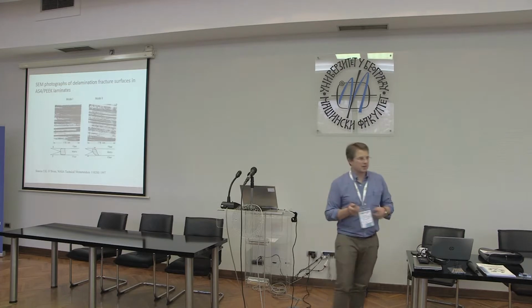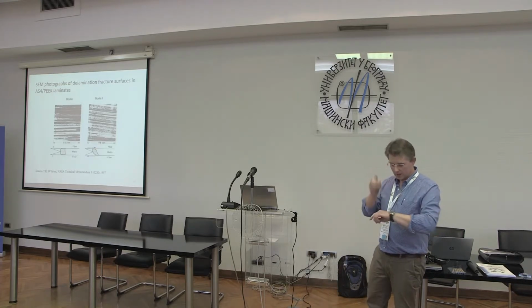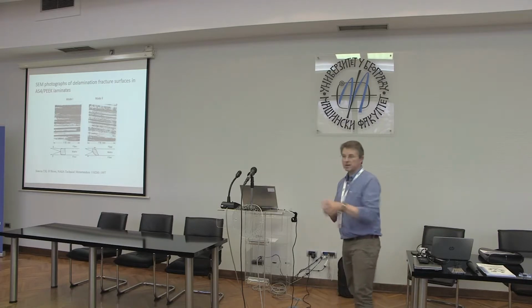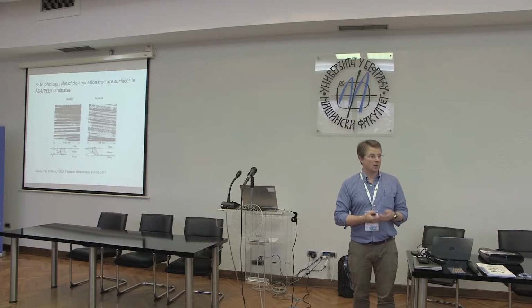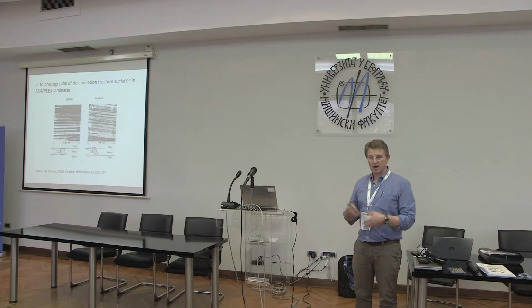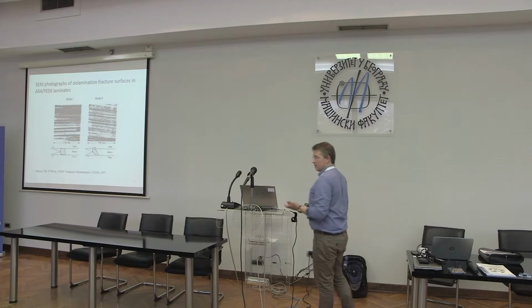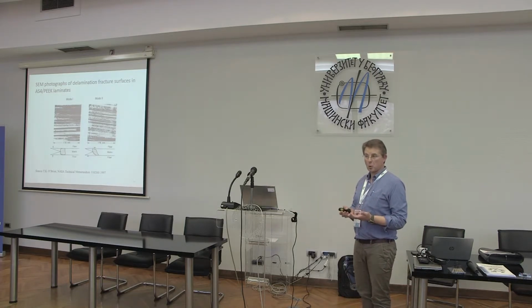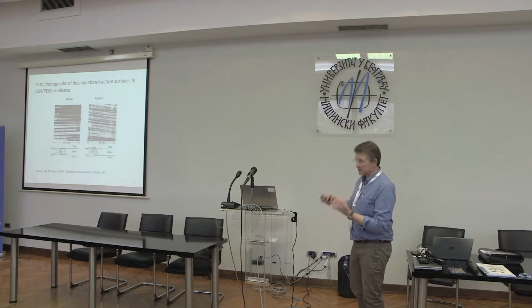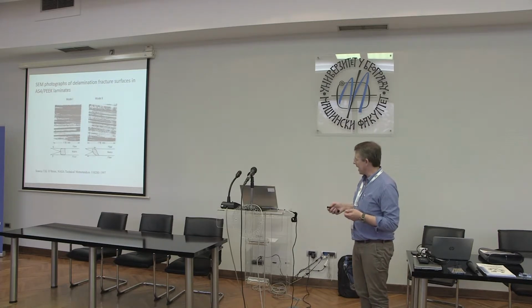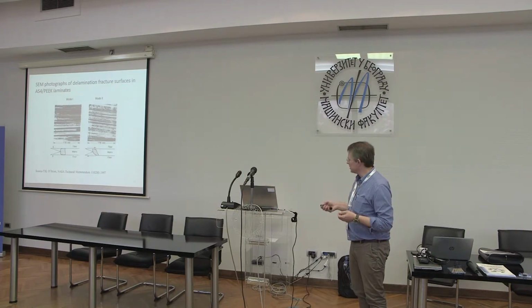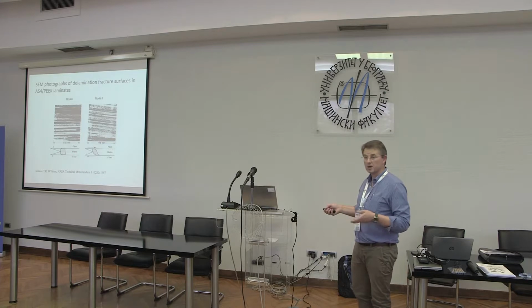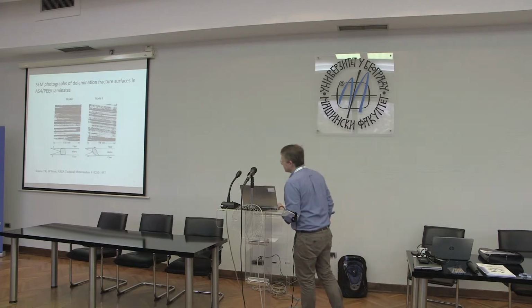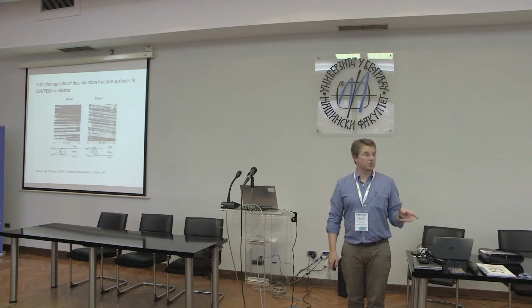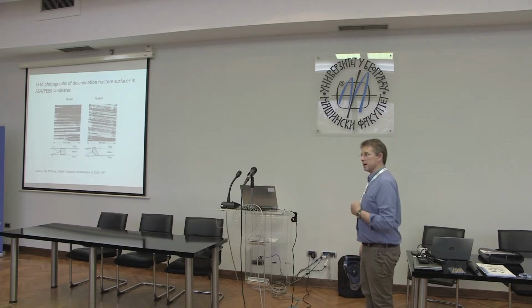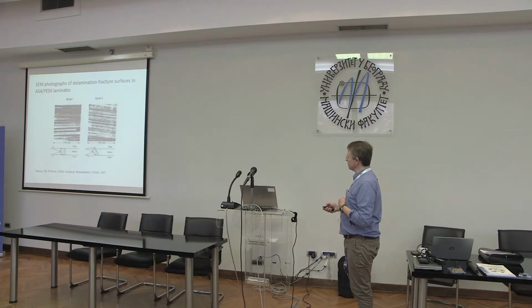So what's interesting is that it's material dependent. So if you go to a tougher system, like in this case we've replaced the epoxy matrix with a thermoplastic PEEK material. So this is now a much more ductile polymer and typically has a much higher mode 1 fracture energy. So if you then just make your material of this and you run a mode 1 crack in, so this is the mode 1 situation, but now we have the more ductile matrix. What we see happens there, first of all, is under mode 1 conditions, we have a larger plastic zone because the material is behaving in a tougher, more ductile fashion.